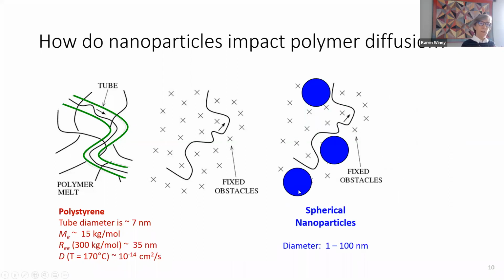We've looked at spherical particles, and we've looked at cylindrical carbon nanotubes and nanowire sorts of particles, but you could see that these particles are on the same sort of length scale as this reptation model. Now, looking at polymer diffusion inside nanocomposites is inherently complex because if the particles are randomly placed, the interparticle distance is not homogeneous. Sometimes they're a little closer, sometimes they're a little further apart, and this has implications for the polymer diffusion.